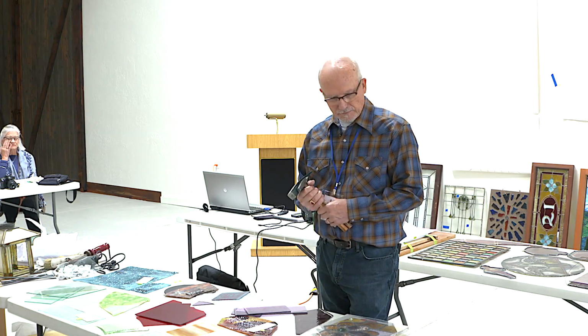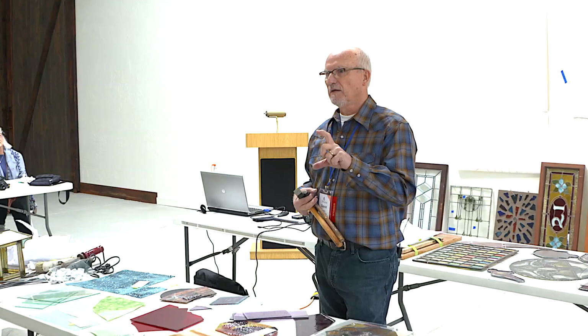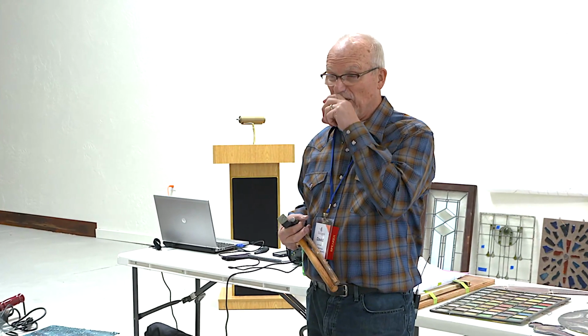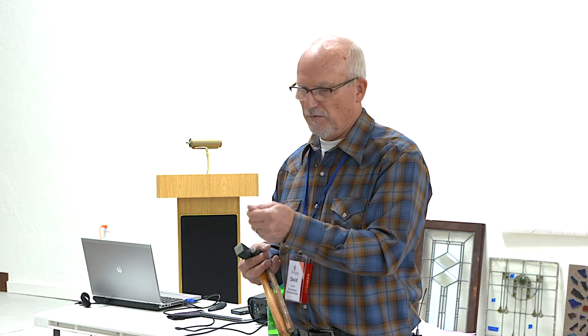Okay. I have to tell you, at Bullseye Glass Factory, I have seen gold coins melted down in a beaker of acid with a Bunsen burner, or dissolved in a beaker of acid, and then you end up with a white powder. And you take that white powder and you dump it into a big 55-gallon drum of silica and your glass, and you melt that down and you get a super dark pink glass. And you roll sheets of that up and you cut them into little squares, and then you can have a furnace of clear glass or a furnace of white glass. And you can take that little piece of pink cullet and throw it in there and watch it melt, and when it gets hot and starts to sink, you grab it with the ladle and throw it on the table and roll it out, and you get a beautiful pink sheet of glass.